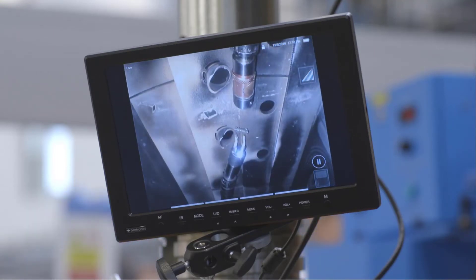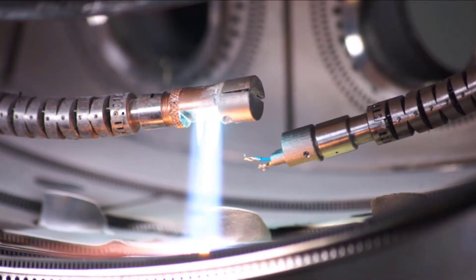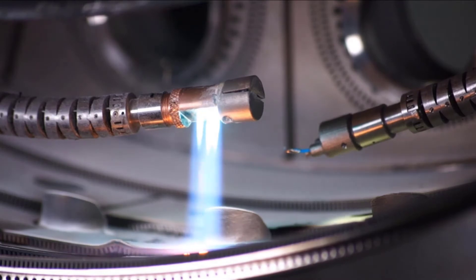Before this, all engines needed to be taken off the wing for repair in the combustor. This is the first time Rolls-Royce has the capability of repairing damaged components inside the combustors. One snake arm contains a camera and an igniter, and another contains a flame spray which can redeposit the thermal barrier coating without dismantling the engine.